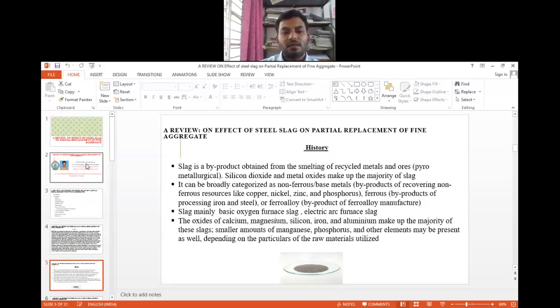The steel slag is mainly formed from basic oxygen furnace slag, which uses oxygen, and the next one is electric arc furnace slag, for which electricity is used. The oxides of calcium, magnesium, silicon, iron, and aluminum make up the majority of those slags. Smaller amounts of manganese, phosphorus and other elements may be present as well, depending upon the raw material utilization. This is a picture of steel slag which we took from near Vizag steel plant.